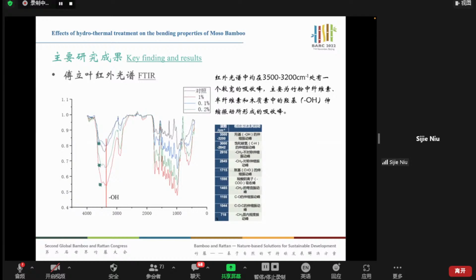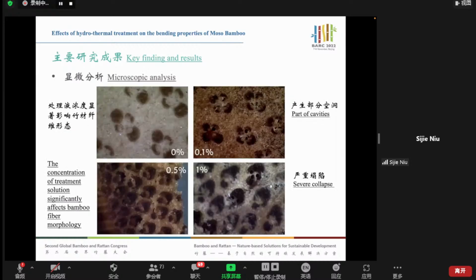This is using FTIR testing method. You can see after this FTIR, there is a significant change in cellulose, hemicellulose, and the lignin in bamboo powder. Without treatment, you can see there is a small absorption peak here. In the interest of time, I would skip the detailed elaboration of this graph.